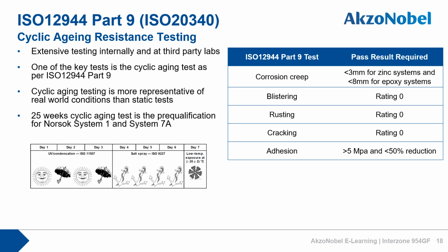For offshore end users, this cycle is repeated 25 times, or 25 weeks. And as we can see on the table on the right, those are the requirements for a system to pass the ISO 12944 test regime. So less than 3 mm corrosion creep for zinc-rich primed systems and less than 8 mm corrosion creep for epoxy systems, and no blistering, no rusting, no cracking, and an adhesion value of greater than 5 MPa pull-off adhesion and less than 50% reduction of adhesion from prior to test to after aging.